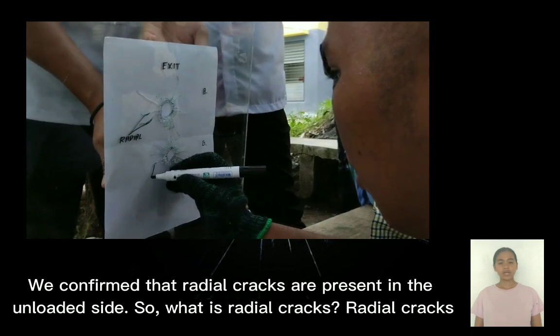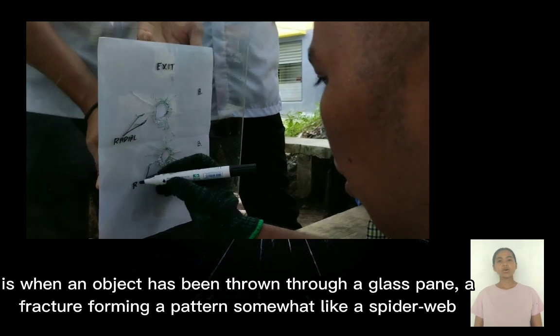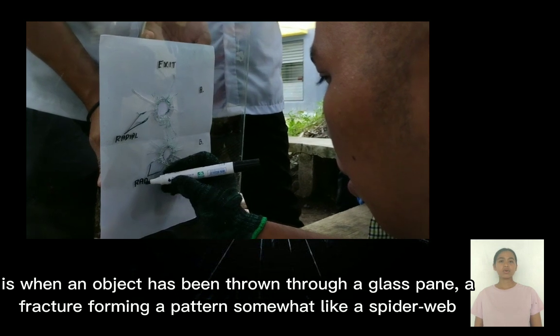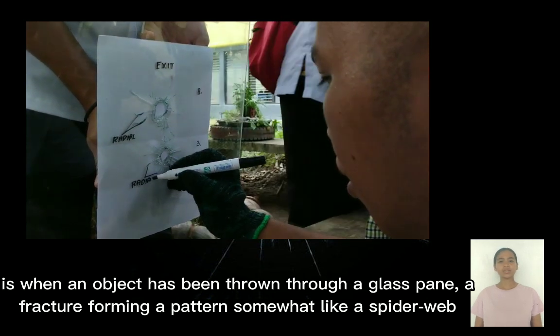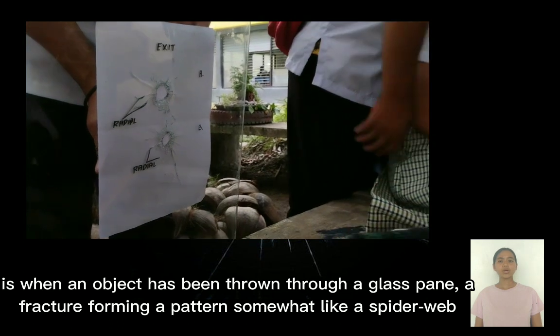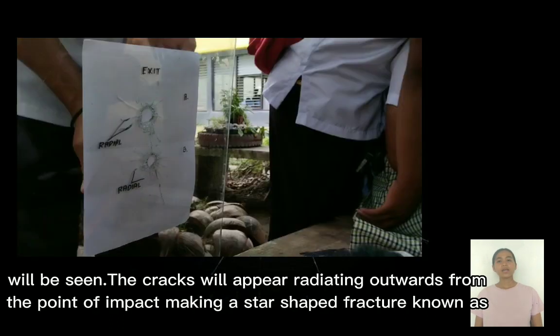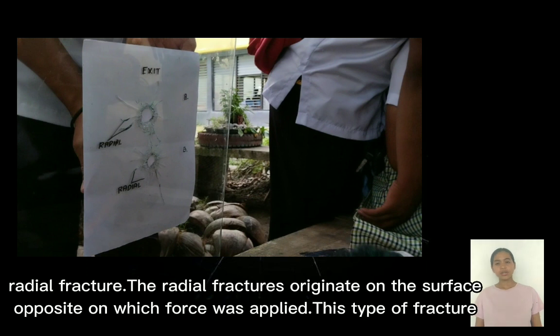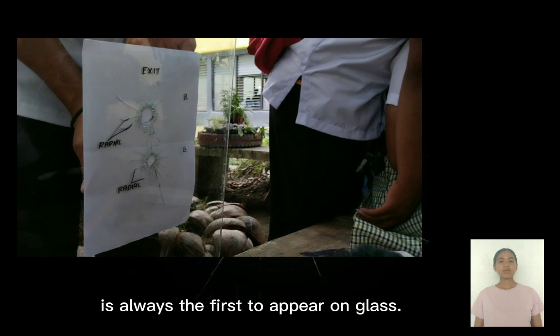So what are radial cracks? When an object has been thrown through a glass pane, a fracture forming a pattern somewhat like a spider web will be seen. The cracks will appear radiating outwards from the point of impact, making a star-shaped fracture known as a radial fracture. The radial fractures originate on the surface opposite to the one on which force was applied. This type of fracture is always the first to appear on glass.